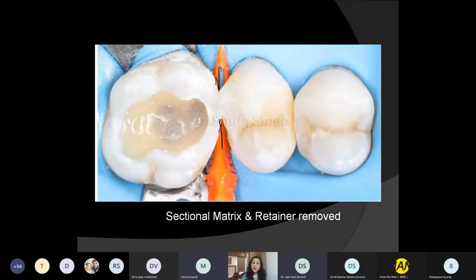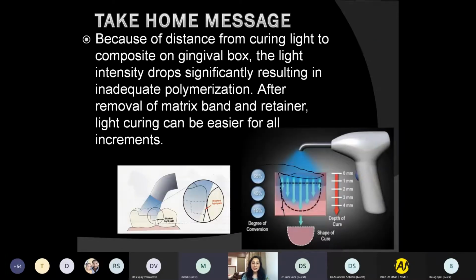And why did I do so? So that the light curing system could be applied on this buccal surface and this lingual surface, so that I can get a good degree of conversion. As the distance from the curing light to the composite in the gingival box increases, the light intensity drops significantly, and this results in inadequate polymerization. So when we remove the matrix band and the retainer, the light curing can be easier for all increments.